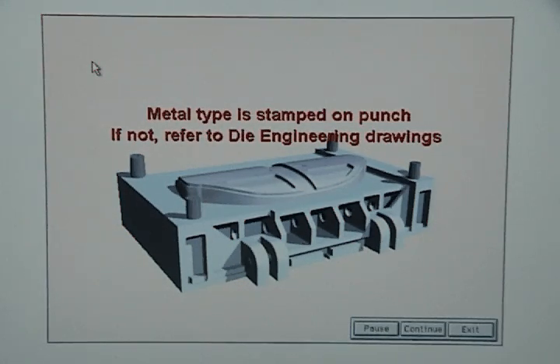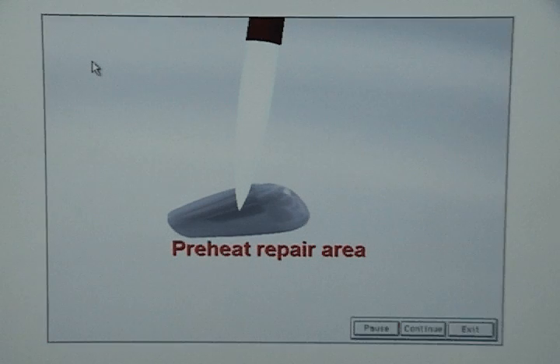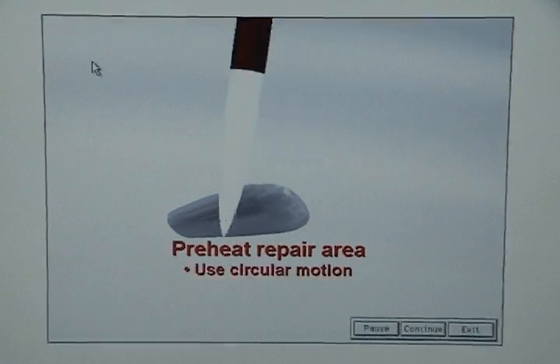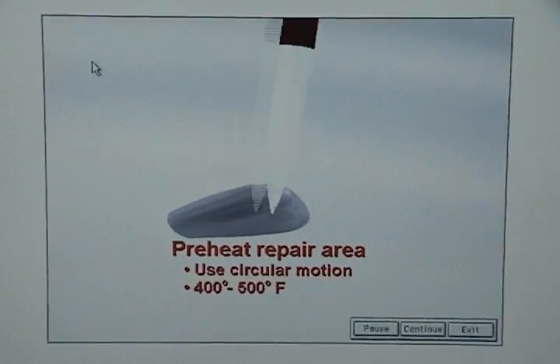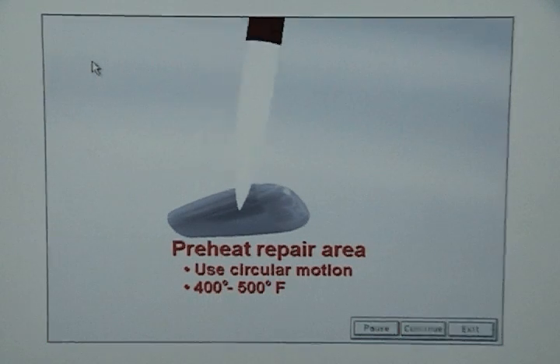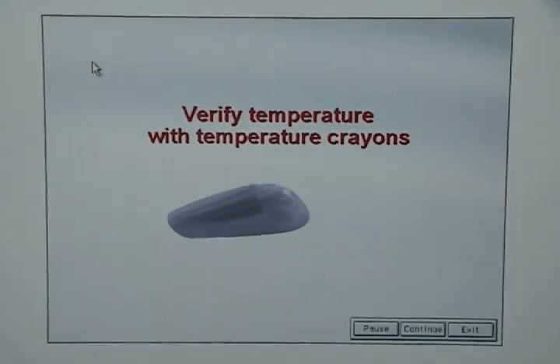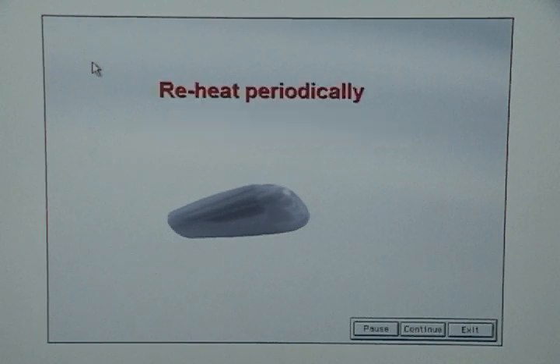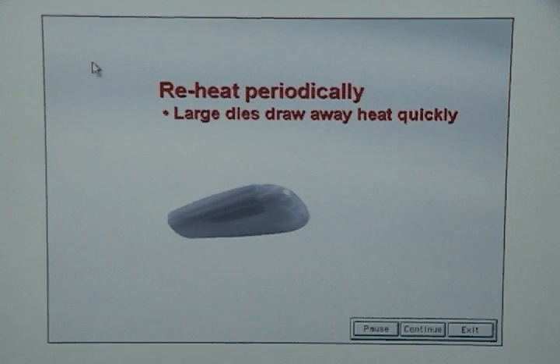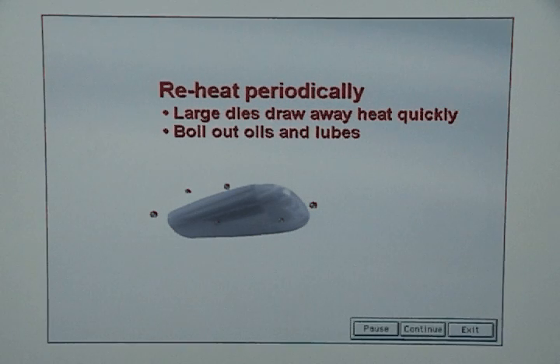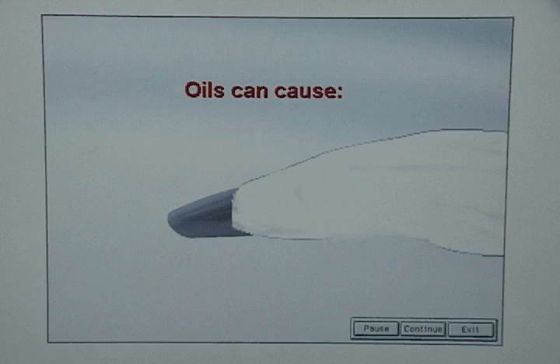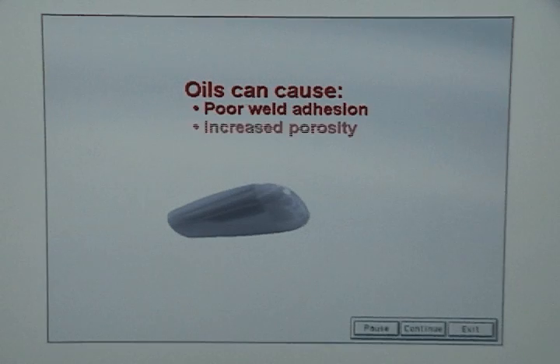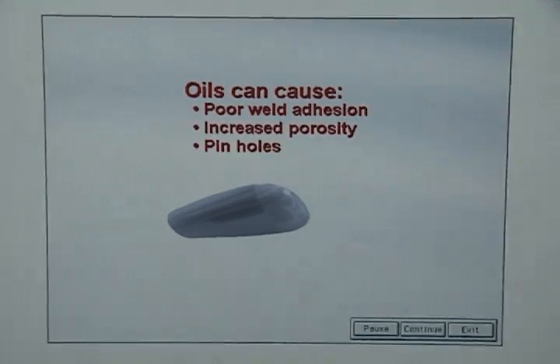engineering drawings. The welder should evenly preheat the repair area using a torch in a circular motion until its surface temperature is between 400 and 500 degrees Fahrenheit. He should verify the temperatures using temperature crayons. The repair area will need to be periodically reheated throughout the procedure because large dies draw heat away quickly. Frequent reheating also boils out oils and lubes that were absorbed into casting pores. Be sure to wipe away these oils because they can cause poor weld adhesion, increased porosity, and pinholes.